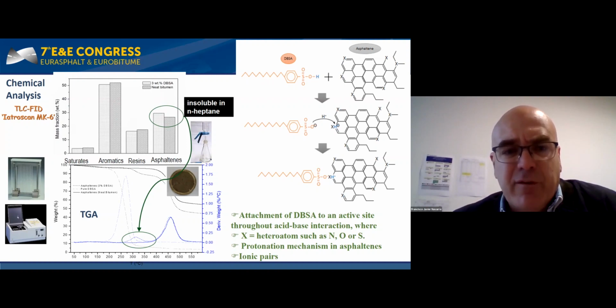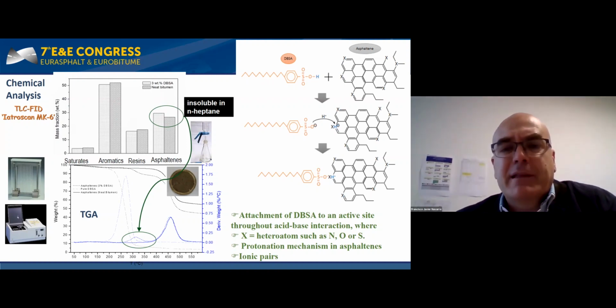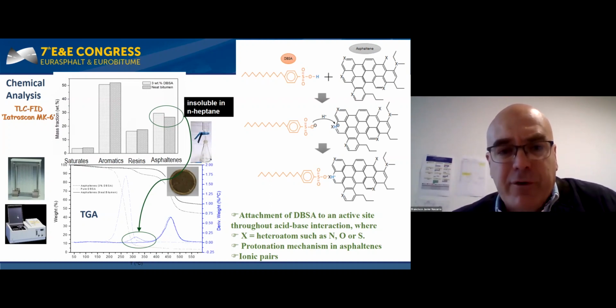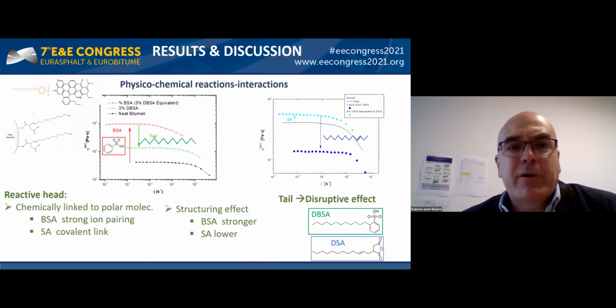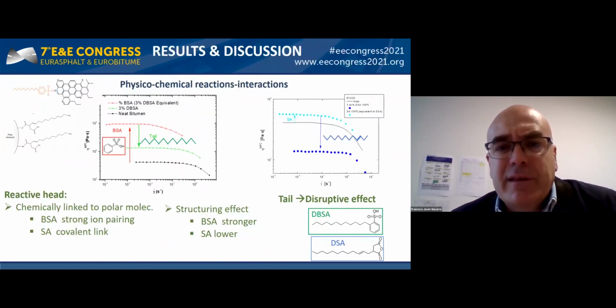In addition, when the insoluble fraction in n-heptane is submitted to thermogravimetric analysis, the derivative of weight loss curves clearly shows the appearance of a new peak, which is associated to the development of the ionic pairs between asphaltenes and DBSA. Consequently, it has been proven that both additives are linked or may be linked to polar bitumen compounds. However, despite they present a similar hydrocarbon aliphatic tail, they produce an opposite modification.